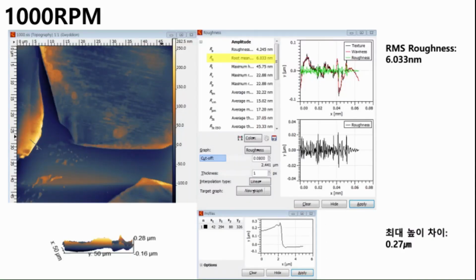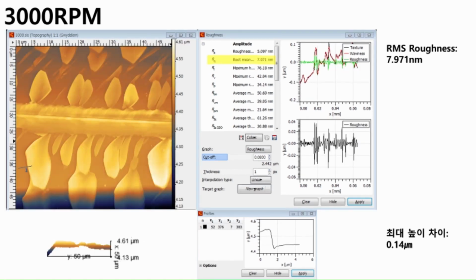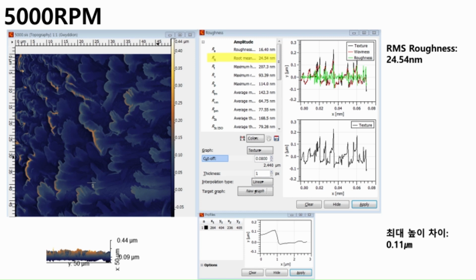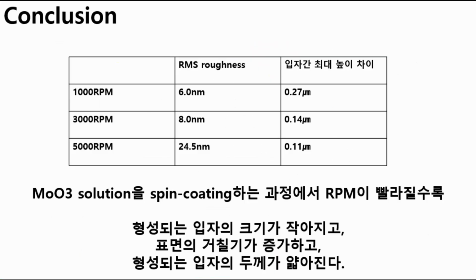Now let's analyze our data. Compare the topography, root mean square roughness, and the height of the sample. We can see that when spin coating is done at higher RPM, the particles become smaller, rougher, and thinner.